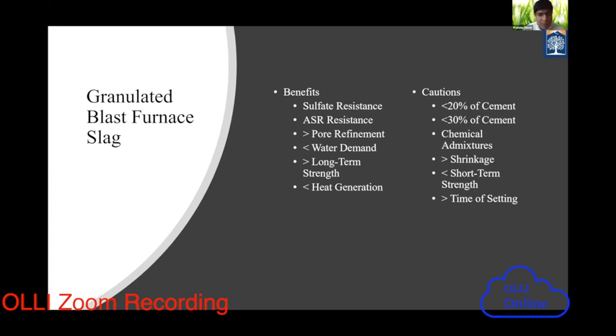Major benefits: it provides corrosion resistance, sulfate resistance, ASR resistance, pore refinement happening, again filling up the voids, less water demand, easy to deal with, providing long term strength, and less heat generation. As it provides less heat generation, it is sometimes also heavily used in mass concrete structures. Mass concrete means dams. Dams go through, as you can imagine, thermal cracking.